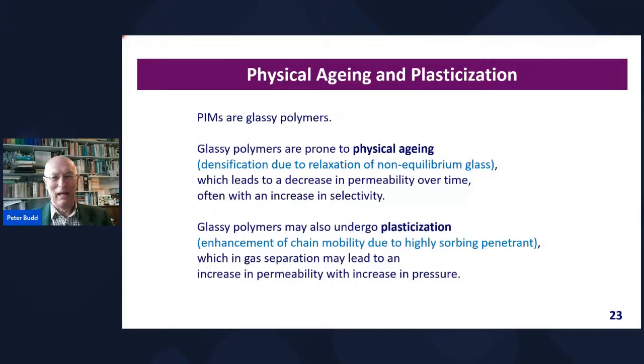And the other thing which we need to be aware of is that glassy polymers may undergo plasticization, and in gas separation it leads to an increase in permeability, often with loss of selectivity as pressure increases. And this is particularly important when we're dealing with strongly interacting gases such as carbon dioxide. So physical aging and plasticization are two things that need to be understood and controlled.